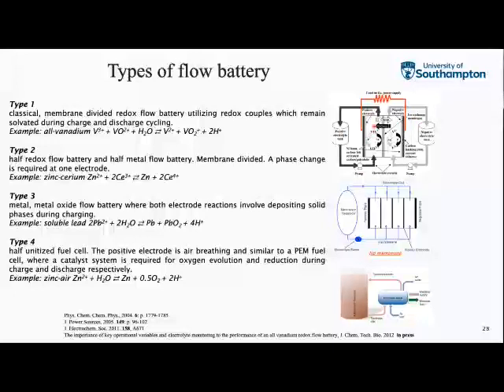So you're shuttling between the oxidation states of vanadium. Membrane is needed to stop the V2 and the V5 self-discharging if they mixed. Another type is half redox flow battery, half metal flow battery, and so you've got a phase change. An example is the zinc cerium system. So in the zinc cerium system, you have a phase change at the negative electrode, and you're electroplating zinc during the charging reaction and dissolving it again during the discharging reaction. So there's a phase change there. The cerium is shuttling between cerium 3 plus, cerium 4 plus, but stays solvated in the electrolyte.